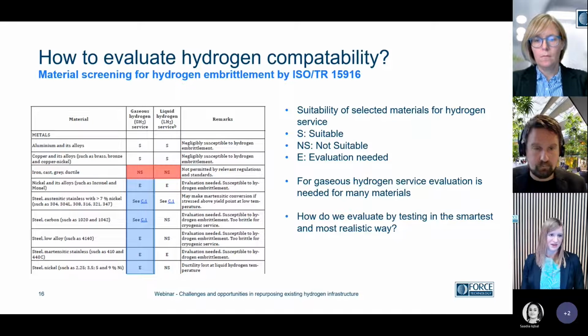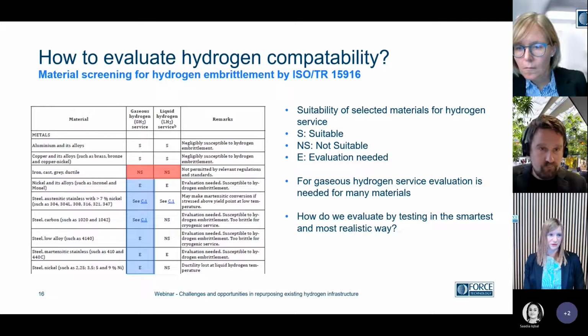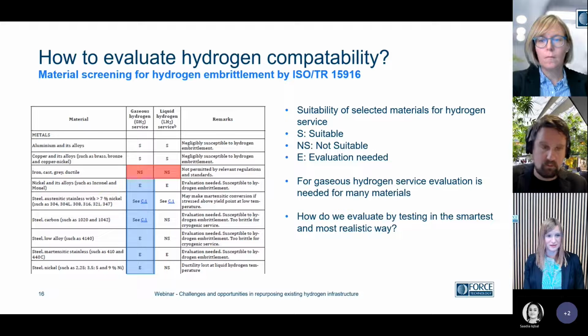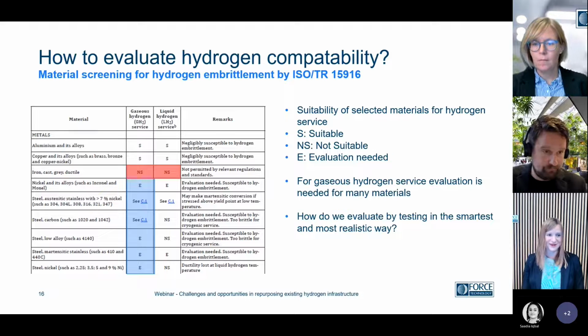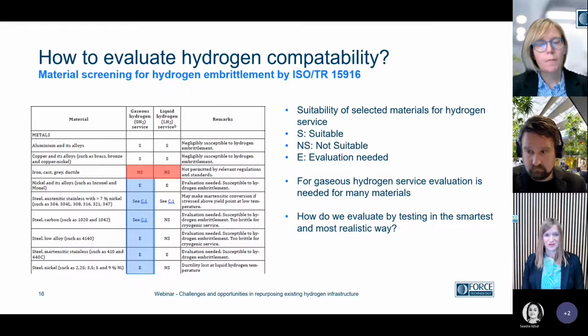Diving a bit deeper, we see that a widely used material like cast iron, ductile iron, is rated not suitable, whereas a range of alloys that we know are already used, austenitic stainless steels, look well, but low alloy carbon steels receive an E, which is evaluation is needed. Through testing would be the best approach. But how do we evaluate by testing in the smartest and most realistic way?